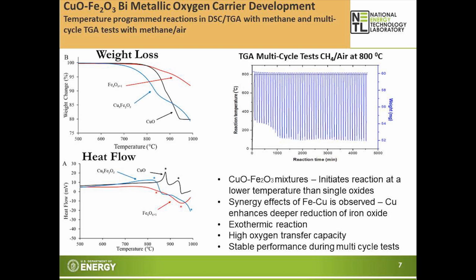And this reaction, these are the heat flow data during the ramp. The reaction is exothermic, very similar to the copper oxide, and it's different from the iron oxide, which has an endothermic reaction. Okay, this is again an added advantage because with the copper iron, we don't have to transfer heat from the oxidizer to the fuel reactor.